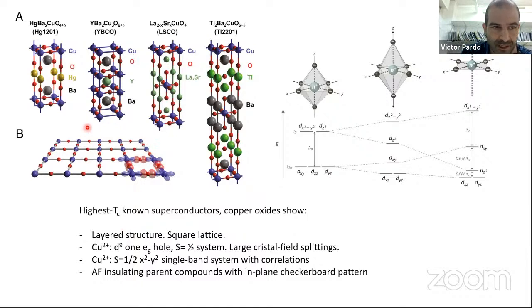First of all, the cuprates appear in different structural families that we have here, but they share some common features. The most important one is the quasi two-dimensional structure with these CuO2 planes. In those CuO2 planes, we have, in the undoped compound, copper 2+ cations. This has 9 electrons in the d shell. So it's one hole in an x squared minus y squared band. And that x squared minus y squared band basically couples antiferromagnetically in the plane. So then the parent compound is an antiferromagnetic insulator in 2 dimensions. And this is common for all the cuprates.